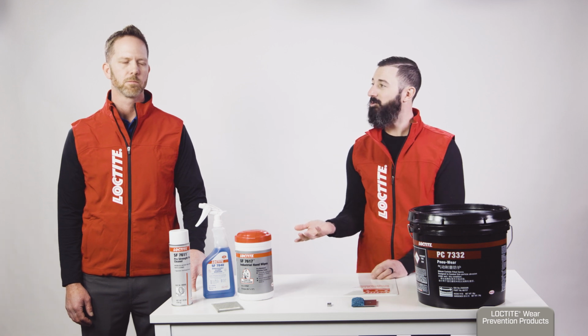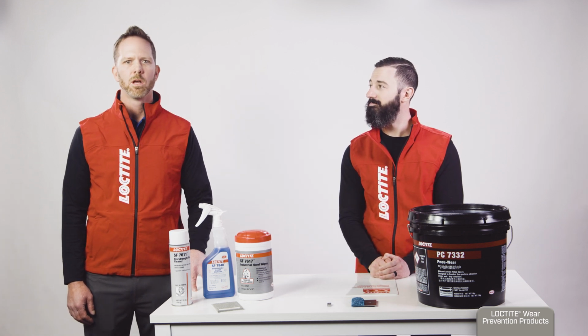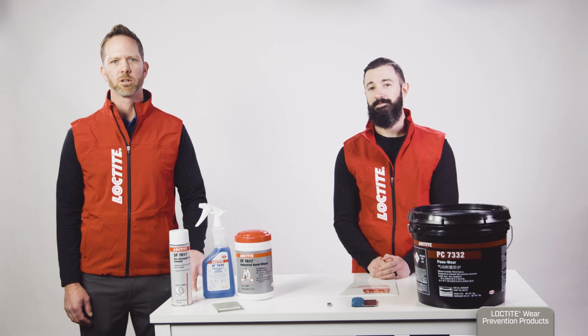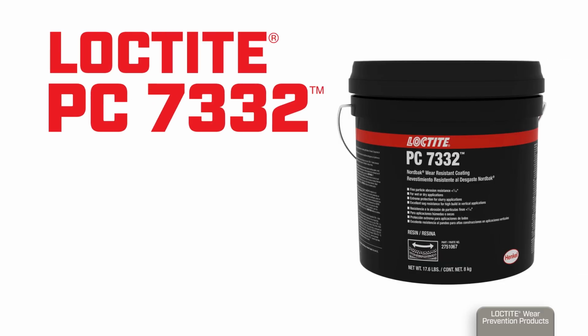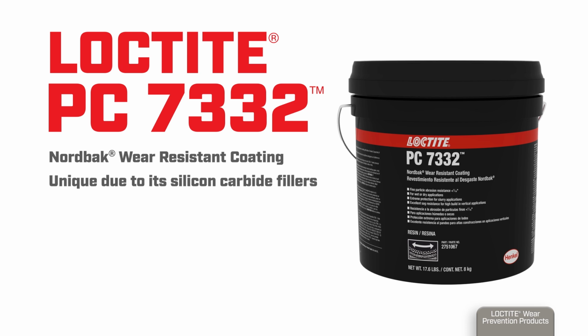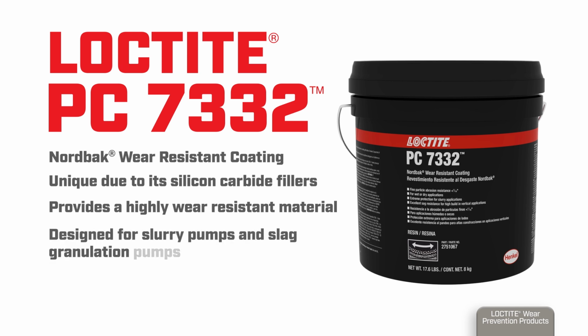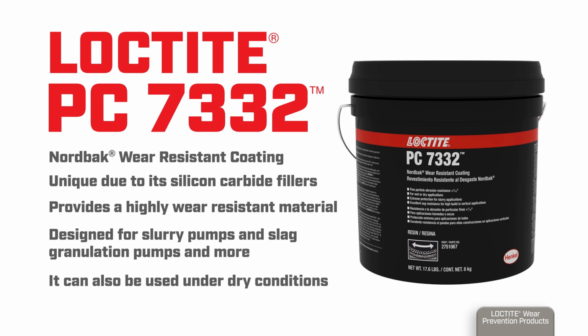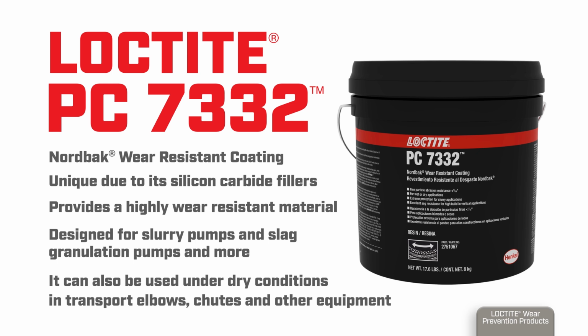Are there any other popular products you see customers using? Yeah, for abrasion on slurry wet materials, we suggest Loctite PC7332, which is the Nordbak wear-resistant coating. This product is unique due to its silicon carbide fillers. The hardness and shape of the silicon carbide provide a highly wear-resistant material, designed for slurry pumps and slag granulation pumps and more. It can also be used under dry conditions in transport elbows, chutes, and other equipment. Overall, this product is great for fine particles both on wet slurry materials along with dry materials.